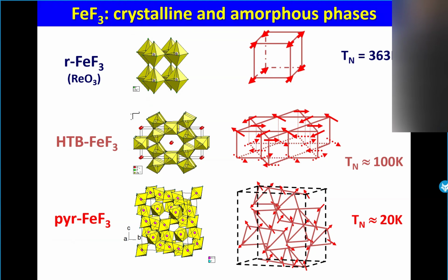Why? Because as you can see, you have some magnetic frustration. Within the planes, you have hexagons with triangles. And in triangles, antiferromagnetic interactions are frustrated. But in between planes, no frustration because you have only square rings. And finally, the pyrochlore contains only triangle rings. So that means the system is completely frustrated. It's a kind of spin glass, 20 K. So that means that the composition is not a problem, but the structure is very important.